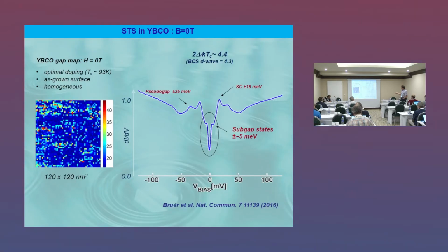And moreover, even without vortices, so at zero field, you see here a gap map acquired on the YBCO, showing that the gap magnitude is quite homogeneous in these samples. And if you take the average spectroscopic measurement over this map, you also see in zero field the occurrence of these subgap states. So obviously these subgap states are not linked at all to the presence of the vortex core.